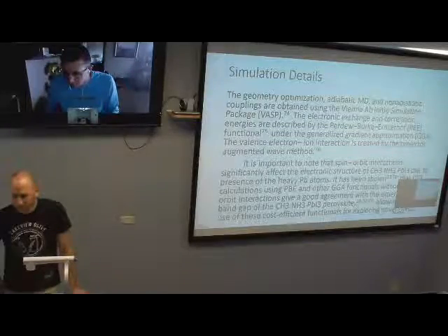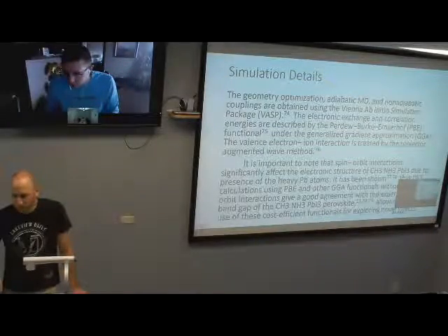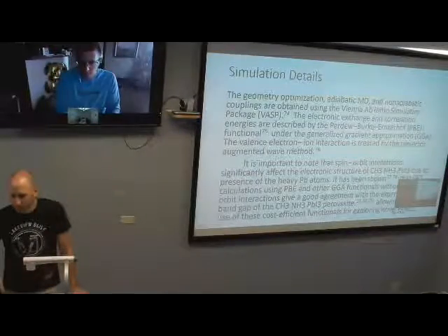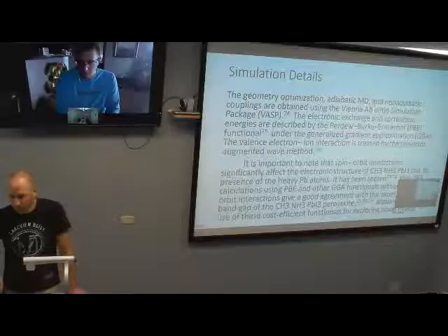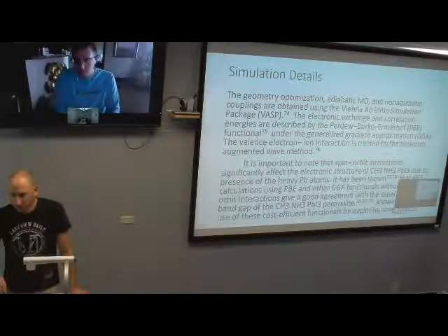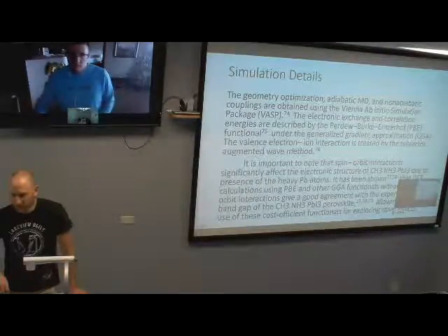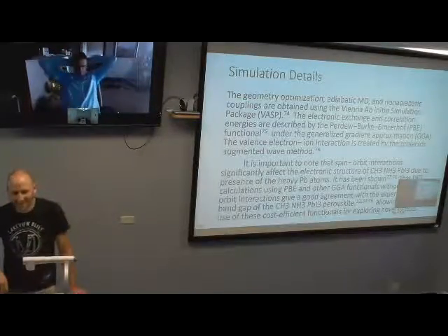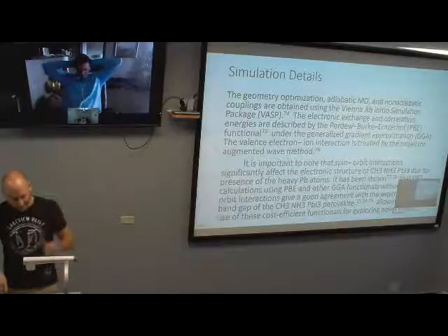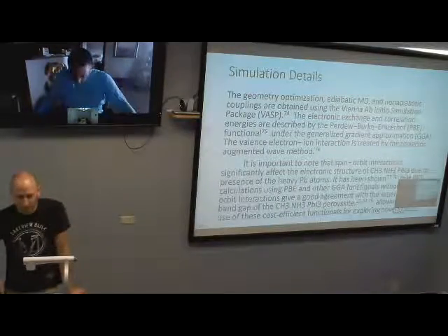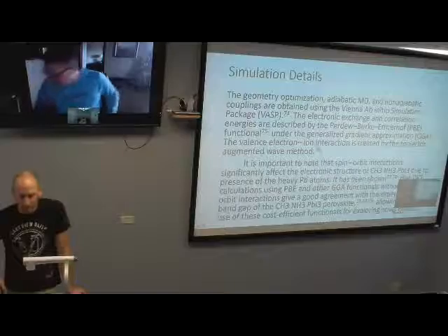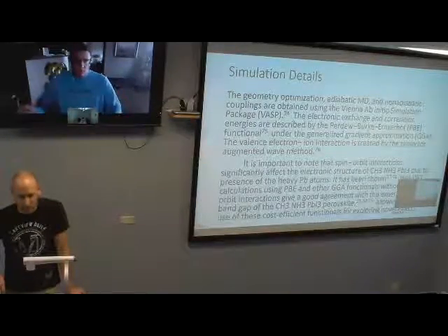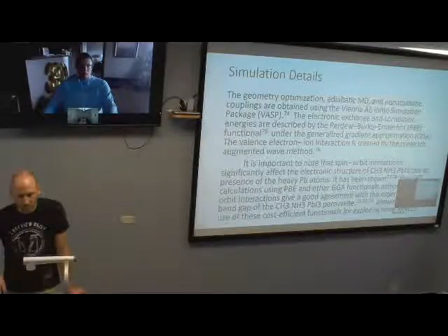There is a cancellation of errors. If you go to hybrid functionals, you need to take into account spin orbit and maybe excitons. But if you do neither of these advanced calculations, you get approximately the right value. Okay, just by cancellation. So again, you get the right value for the wrong reason, right? Yeah. Be careful. As theoreticians, even getting the same number as an experiment doesn't necessarily mean your method is really accurate. In this case, it looks like a cancellation of errors.